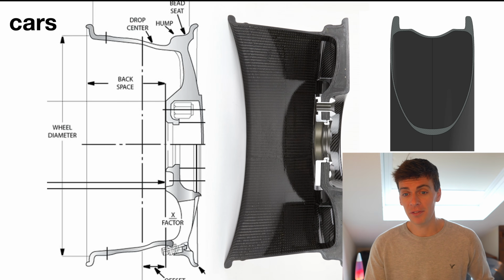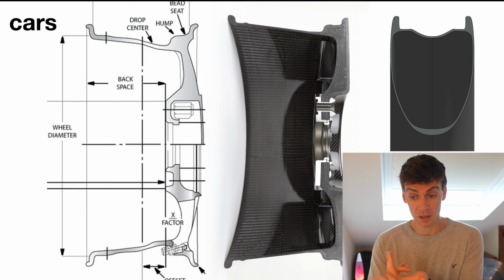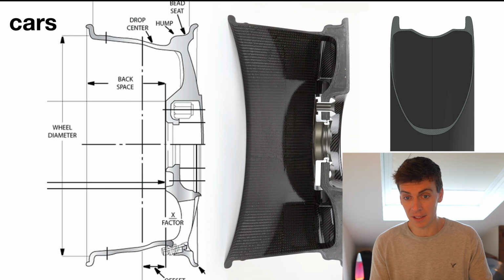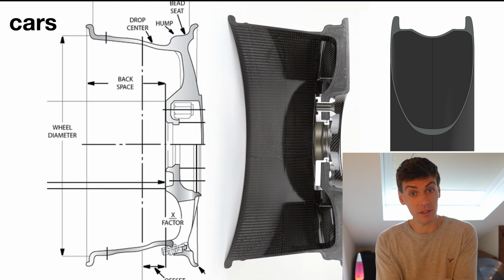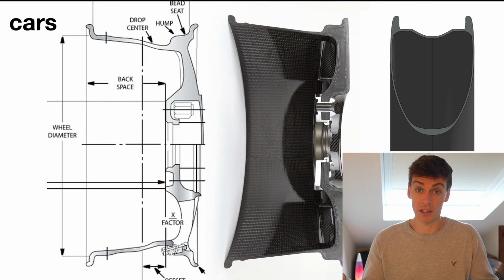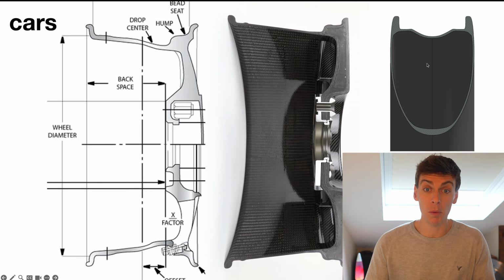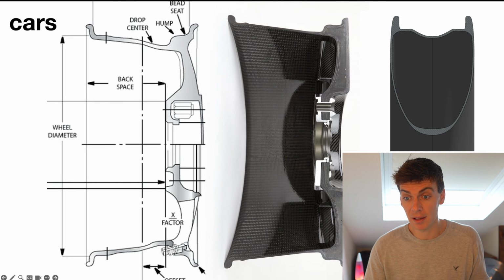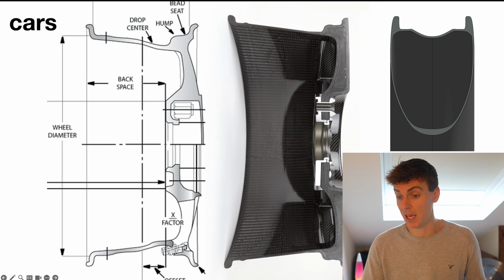Exactly the same. First of all, in bikes, we're still using essentially cross-ply tires, which is a technology only slightly less primitive than solid rubber tires or wooden cartwheels. And in cars, they're radial. They're completely different. The beads in our bike tires are floppy as shit because we want to be able to put them on with our thumbs, whereas a car you need basically a hydraulic press to mount a bead. Well, obviously the car tire has steel beads as well, and radial belts which roll over the top of the bead, over the top of the tread and under the tread to actually hold the structure. We don't have that in bikes, they're made of cotton and piss.